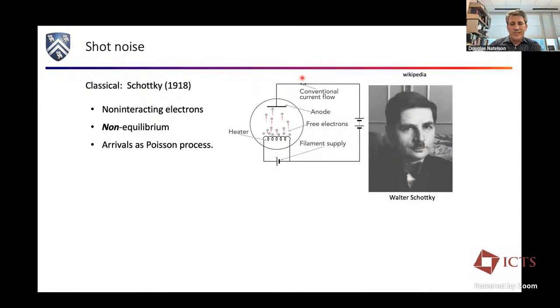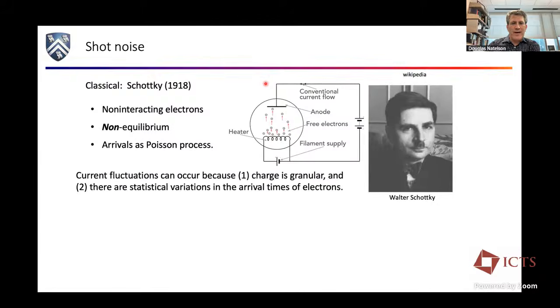Shot noise was originally discussed in charge flow by Schottky over 100 years ago, who was worrying about vacuum tubes. The idea is you can just ask, if I have a Poissonian source of electrons, with some average arrival rate in a system that's being driven out of equilibrium, I can do the statistical mechanics and figure out the statistical variations in the current, because the charge is coming in discrete pieces. If you talk about the charge current noise, the mean square fluctuations in the current per unit bandwidth, with Poisson statistics that has the form 2e times the average value of the current, where e is the charge of the electron. The noise is frequency independent out to some cutoff that is way beyond what we care about in these experiments. So basically you have white noise, for Poisson charges flying through space.